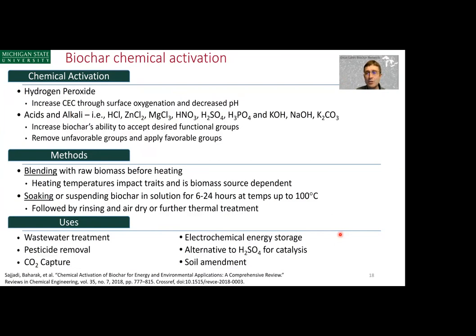For example, you might elect to increase the cation exchange capacity by oxidizing the surface of biochar using hydrogen peroxide, in which case you're using a chemical activation approach. There are a plethora of chemical activation approaches that involve acids and bases, where the goal is to change the types of functional groups, to add or subtract functional groups from the surface of biochar. There are lots of end uses for these, from electrochemical energy storage to pesticide removal. It can improve biochar as a soil amendment, for example, if you increase the cation exchange capacity.